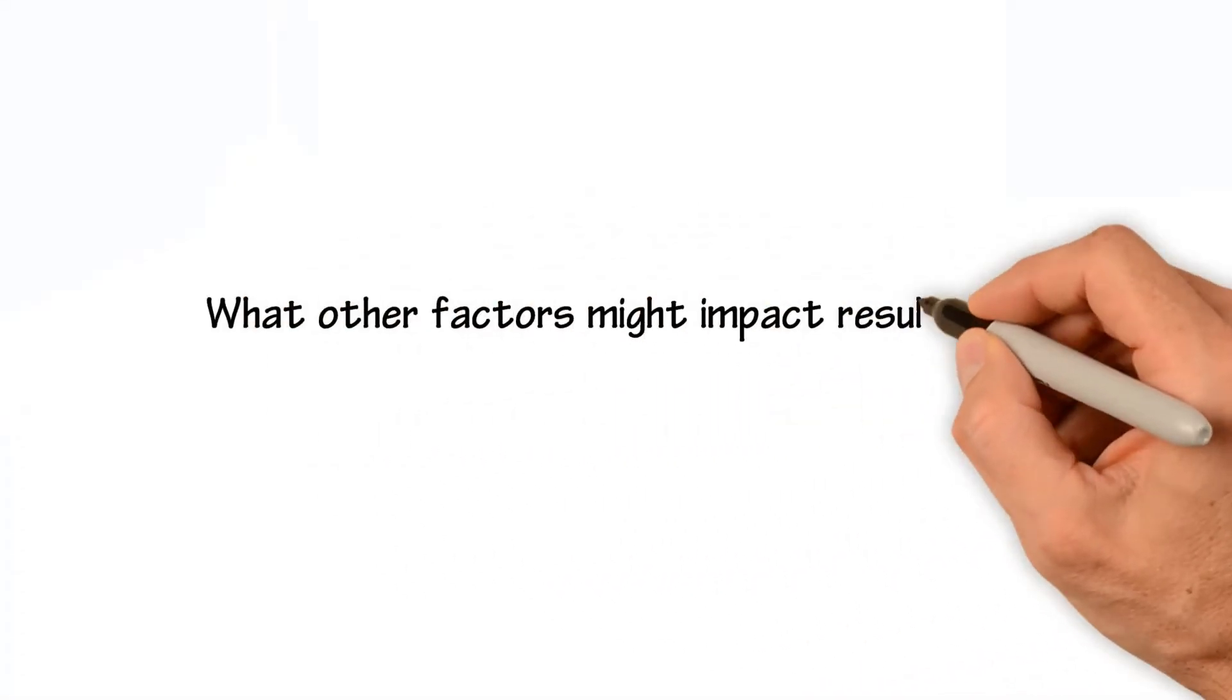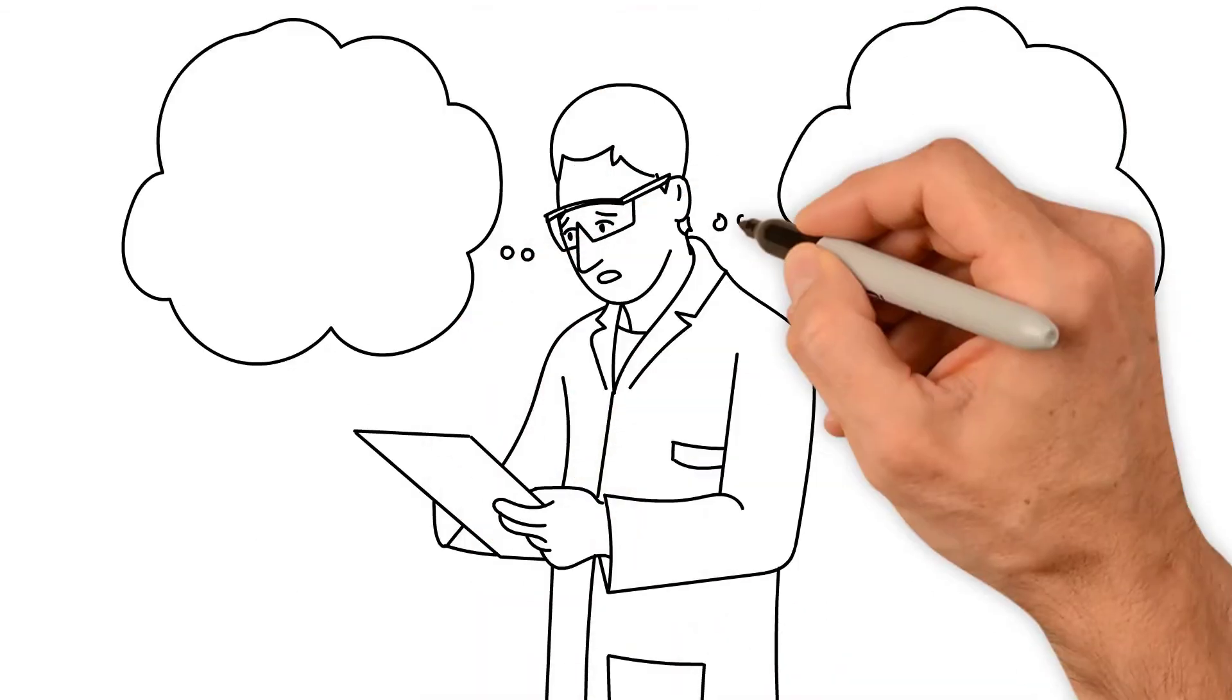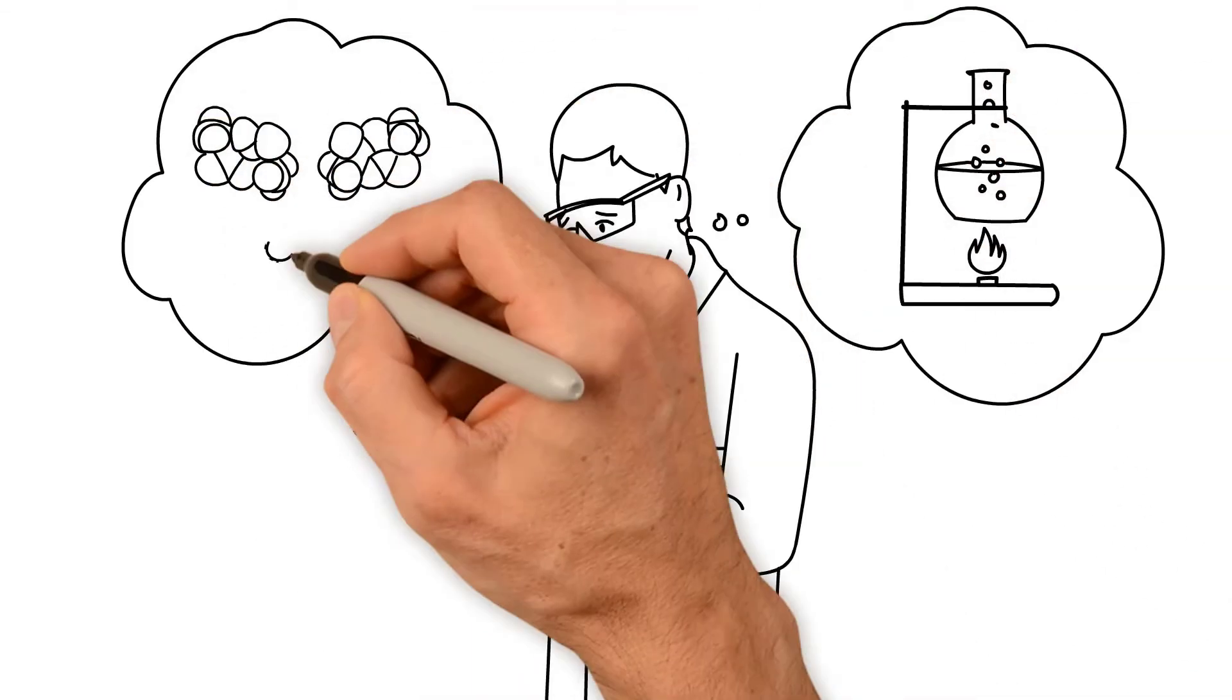What other factors might impact results of flash and fire point tests? Results will be higher for oils that have higher molecular weights, viscosity, and boiling points.